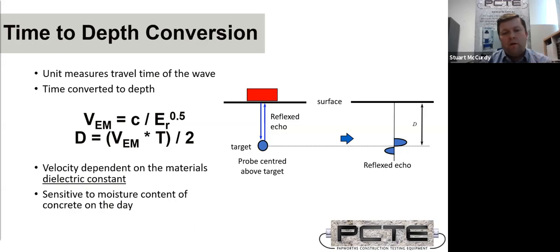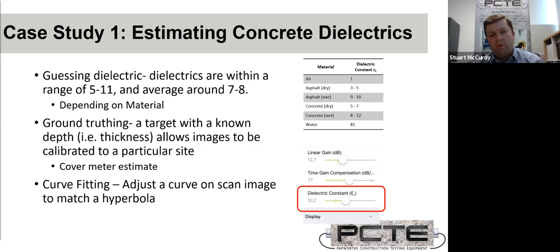how quickly the signal travels in the concrete. Each material has a property called dielectric constant. And the more moisture that you have in concrete, the different your dielectric is going to be. So for GPR, the depth of your targets is affected by the moisture content of the concrete. For cover meters, the cover measurement you get is going to be affected by the amount of steel that you're measuring in the area. So for cover meters, our challenge is to use some techniques we'll get into to isolate a single bar. For GPR, our challenge is to figure out what the actual dielectric of the concrete was, so how much moisture was in the concrete, to get an accurate depth. Location's always going to be accurate, but depth we can improve on.